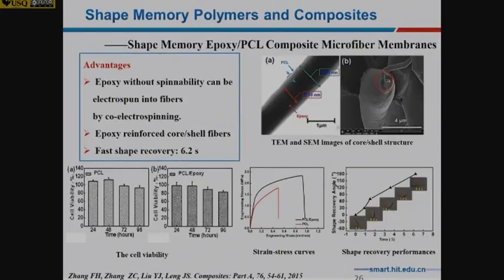And also this one we made, the core-shell shape memory polymer fiber. The initial idea is we have the shape memory polymer which is made by epoxy. It's a shape memory, but this one is not biocompatible. So we make a core-shell with PCL together. So with this one, you can have a biodegradable property, biocompatible property, and also this has a very fast shape recovery time.